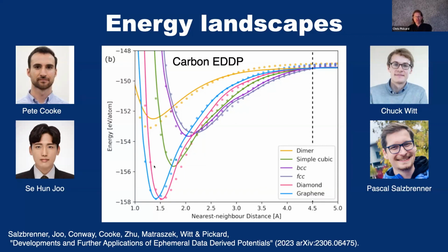on a supercomputer. And without trying, because of the simplistic representation of the potential, it just automatically came out smooth. Not perfect. Our lines don't perfectly align on top of the DFT data. But from the point of view of searching for new structures, it's getting most things right, even for strange structures. So this is reassuring. Actually, it was Se Hun Joo who did these sweeps for our potentials and compared it to the work of Ralf Drautz.